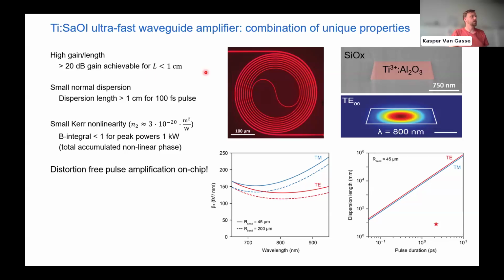On top of that, the material dispersion is quite limited. It's pretty small. And that, combined with the fact that the amplifier is quite short, you can see, if you look at the pulse duration versus dispersion length in this graph, if you ever worked with this, that for this amplifier length, you can amplify pulses as short as 100 femtoseconds and still get away with almost zero dispersion on the pulse. So that means that we can really amplify ultra short pulses with this amplifier without any degradation of the pulse.